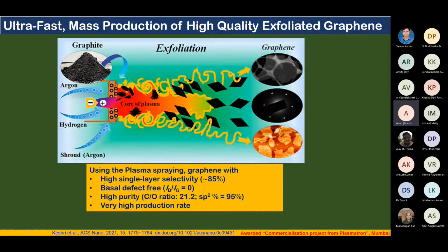From the plasma spraying, for the graphene which we have got, after doing multiple analyses, we have found that the single layer selectivity was around 85% single layer.